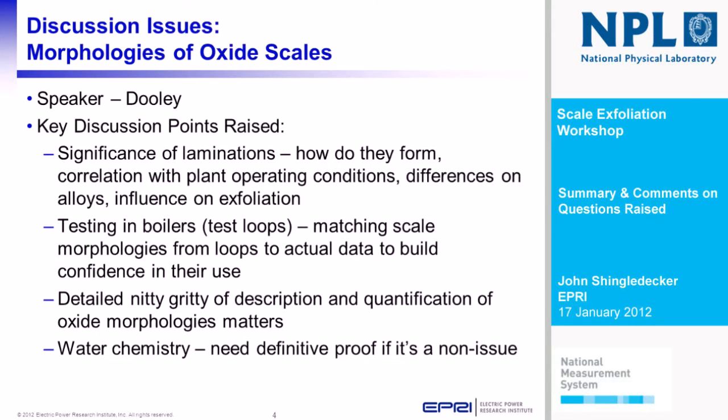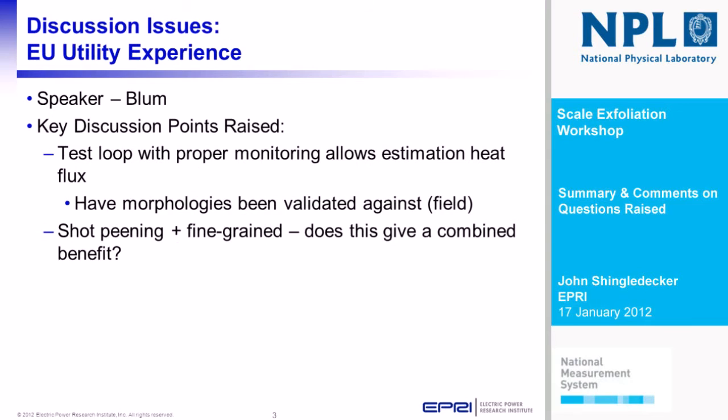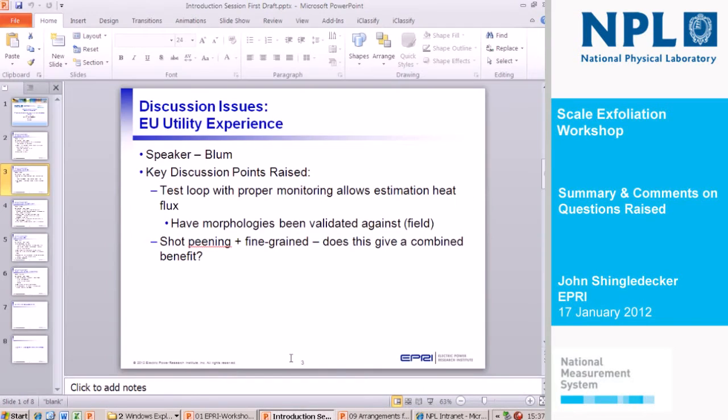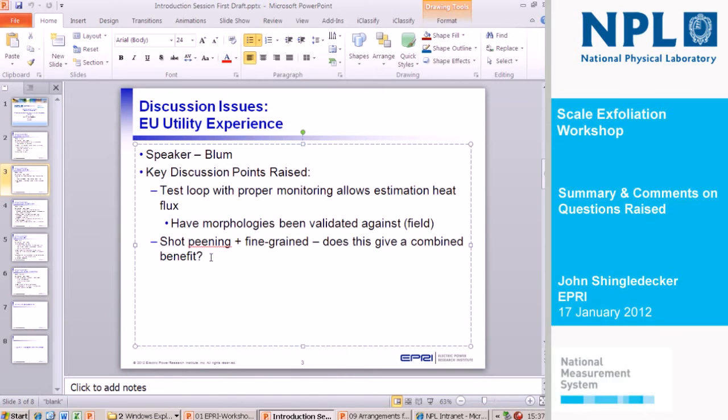I would add composition to that paradigm, because if you're really going to do a cost-benefit analysis, you need to add in what if you could make it all go away by making sure your chromium and nickel contents were at the high end of the spec. You wouldn't have to worry about whether the grain structure was a certain way or being done correctly.